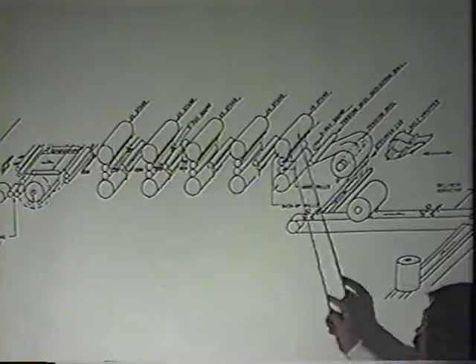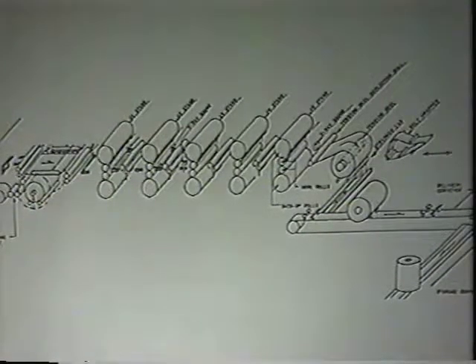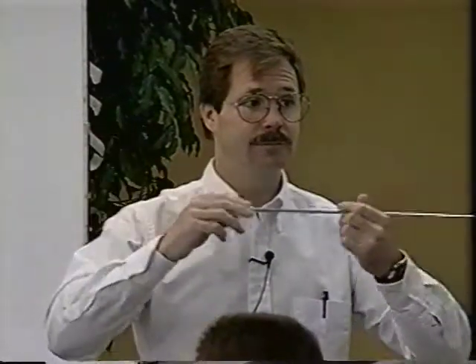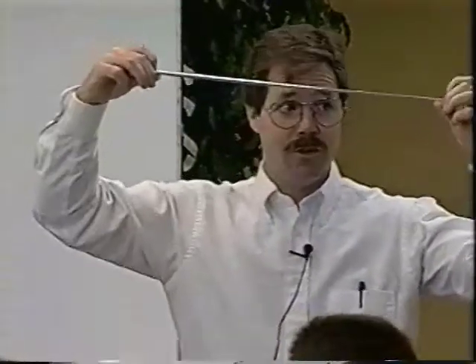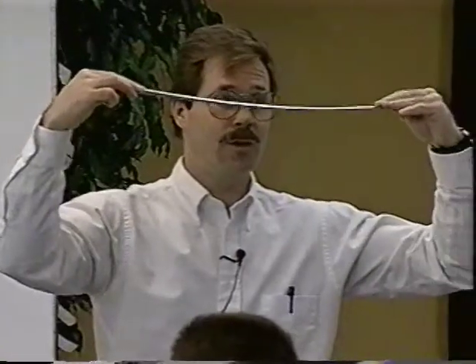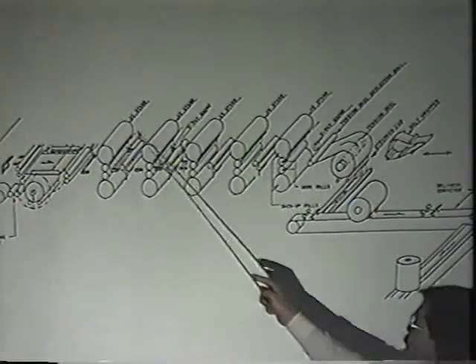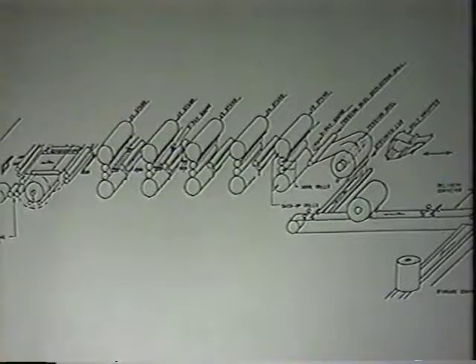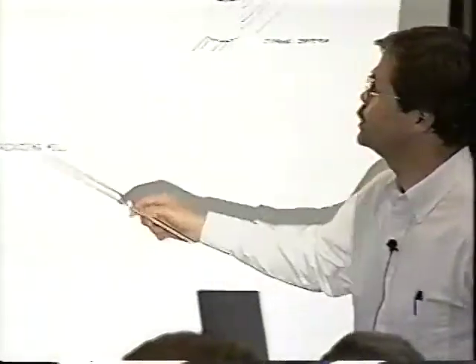What you don't see on this mill is a thing called work roll bending. It was added to mills about 10 years ago to, again, help control the uniform reduction of the strip across the width. Work roll bending is nothing other than a force applied at the rolls to try to straighten them out. If the roll is intending to bend this way because you've got force on the outer sides pushing down, work roll bending provides a counter force to straighten it out. Some mills, to control this whole thing, are now being built as 6-high mills: 2 backups on the top, 2 on the bottom, with work roll bending. Those are the more modern mills. This is strictly a 4-high as it shows here.